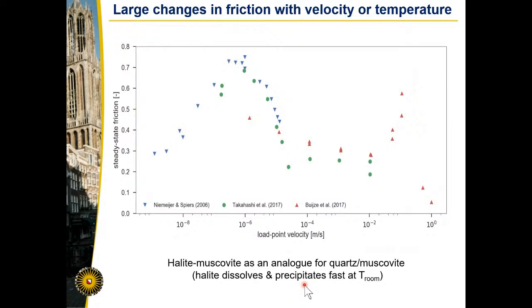Now, to shift gears yet again, how do we take into account these fluid rock interactions? So a long time ago, we did experiments on rock analog materials, because for a lot of the mineral reactions, you need quite high temperatures and long duration experiments to be able to study their effects. So it's nice to have materials that you can use as an analog so that we can do experiments on a reasonable time scale and preferably at room temperature as well. So we do experiments on halite, rock salt, which is an analog for quartz, because it dissolves and precipitates really fast at room temperature. So we can study this process under easily accessible laboratory conditions.